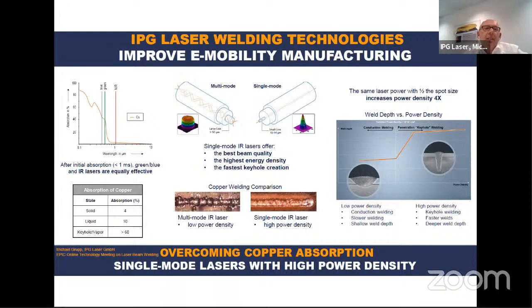And at the same time, when we then go very fast with this high power density, we can create very stable processes. As I cannot point now with my mouse, you have to look at the center. I have to explain where you should point your eyes. So we see a very stable weld on the right side and a very unstable weld on the left side. On the one side with a low power density, on the other side with a high power density, which means as soon as we create a stable keyhole, we also can create a stable welding process.